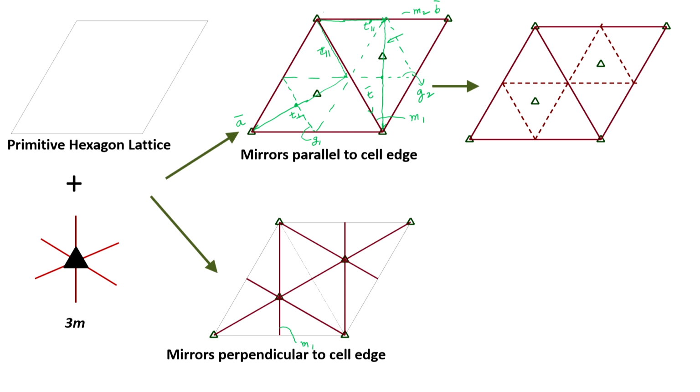Now, let us look at a particular operation, reflection operation sigma 1 across mirror 1, follow it up with the translation vector A. So, my translation vectors are A and B here. Now, let us look at this vector A. This vector A can be broken up into two components. The parallel component is along the mirror. So, this is my parallel component, and the perpendicular component is along one of the cell edges, T perpendicular.